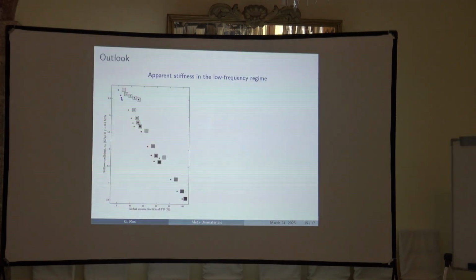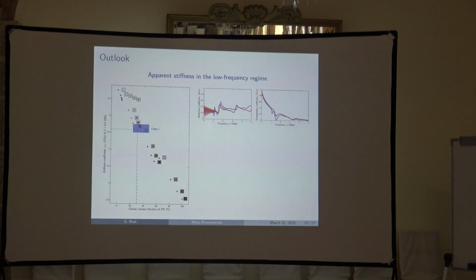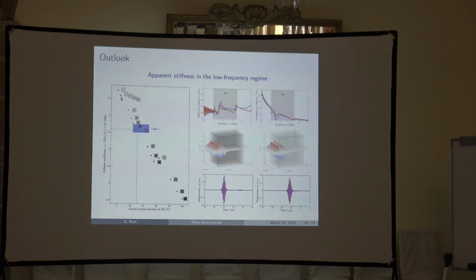And this is not true, because if you put every sample, for instance, on this chart where you have the volume fraction and the equivalent stiffness coefficient obtained from classic homogenization, there is a separation, but some configurations are almost confused, meaning that two very different configurations have almost the same stiffness, and this cannot be discriminated using only low frequency values. I'll go fast on that, but the acoustic behavior at high frequency is able to discriminate cases that, when you homogenize, have exactly the same elastic properties at low frequency. So the low frequency part of the graph is almost superposing. The high frequency is not.